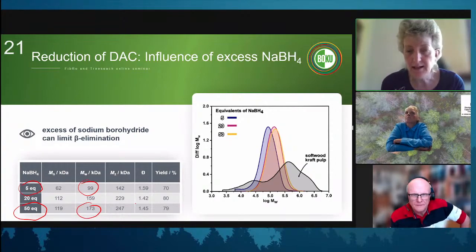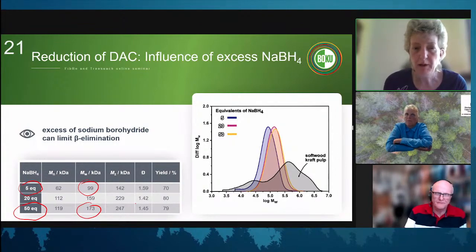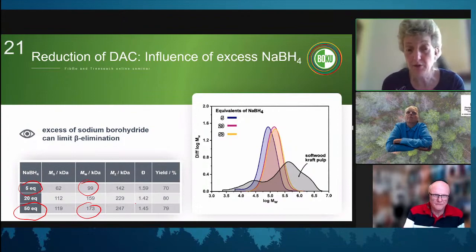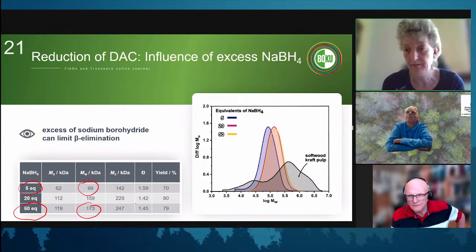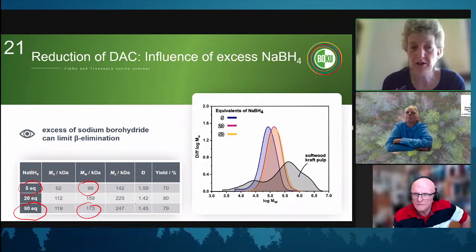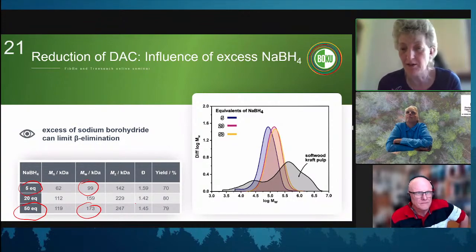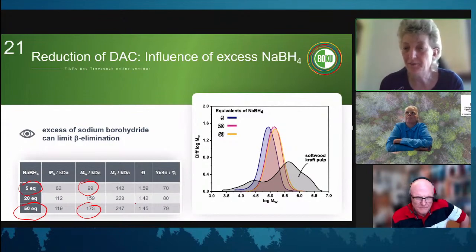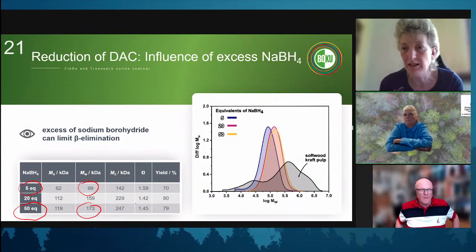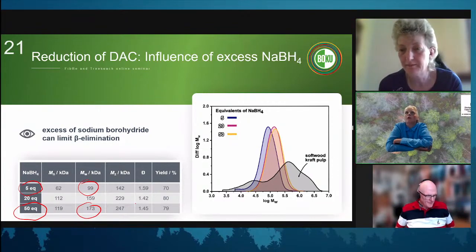For the dialdehyde celluloses, it goes down, of course, with the degree of oxidation. But if the recovery in the process is really bad, then we don't use the data. Because then it also means you don't dissolve a lot. So there is a limit to it. If recovery drops under a certain point, it doesn't make sense, because the question is, where's the rest of the sample? If the rest of the sample is 80% and you only recover 20%, it's meaningless. Yeah, I fully agree.